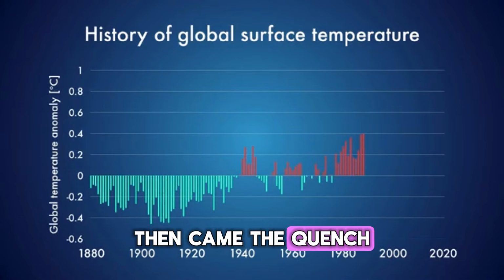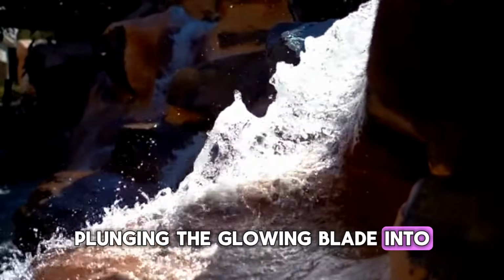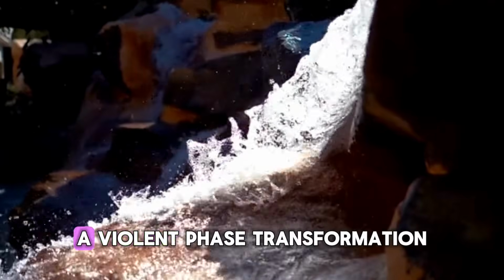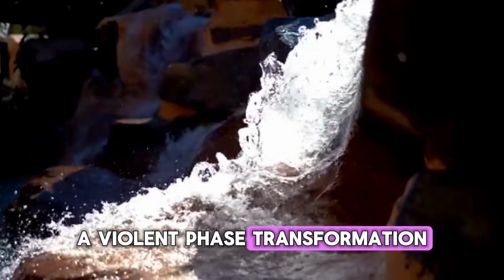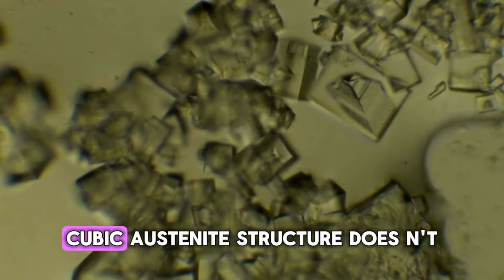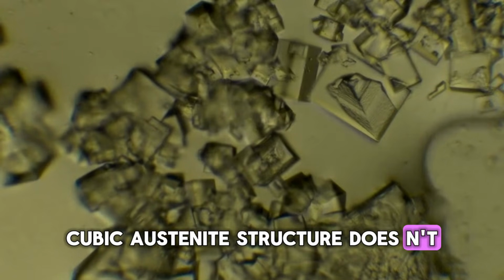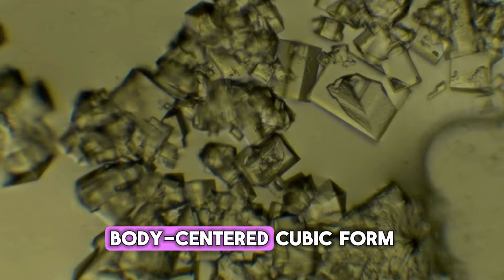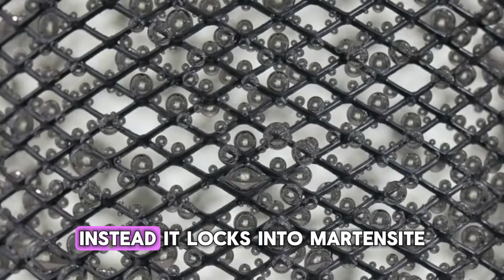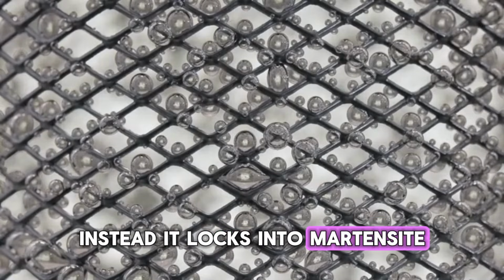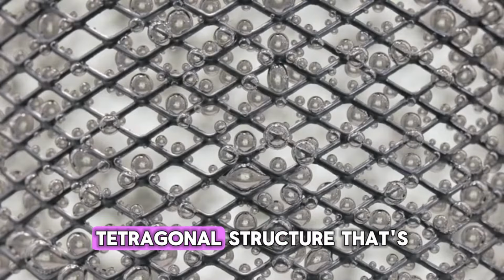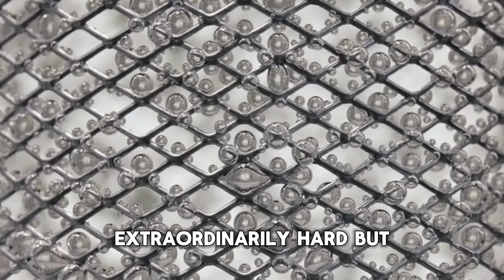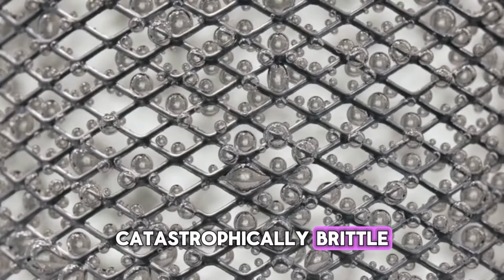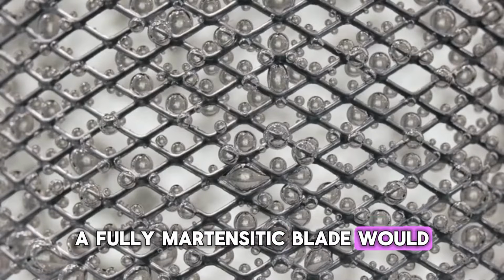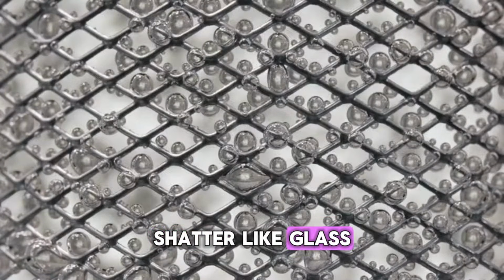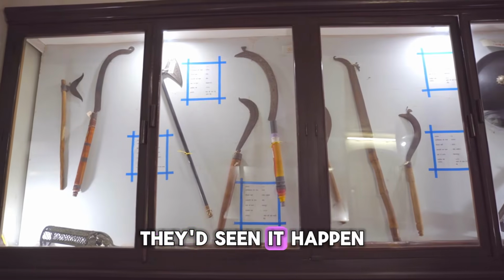Then came the quench. Plunging the glowing blade into water or oil triggers a violent phase transformation. The steel's face-centered cubic austenite structure doesn't have time to revert to its normal body-centered cubic form. Instead, it locks into martensite, a body-centered tetragonal structure that's extraordinarily hard but catastrophically brittle. A fully martensitic blade would shatter like glass. The Romans knew this because they'd seen it happen.